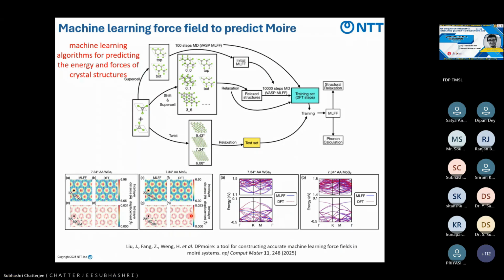Using machine learning, other researchers can determine which angle is appropriate for the material to have the Moire structure, like WSe2 and MoS2. These people did DFT calculations and determined the Moire structure angle for WSe2 around 7.34 degrees and for MoS2 around 7.34 degrees, and calculated the band gap using DFT and MLFF, a machine learning technique. They compared those two values, and they match.